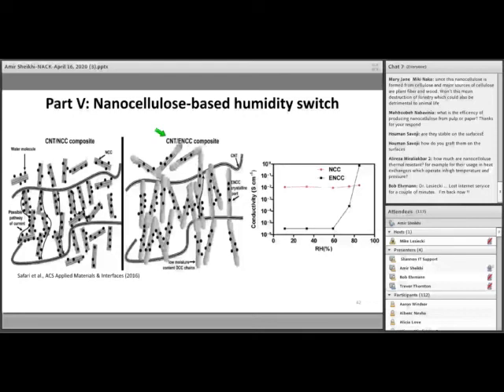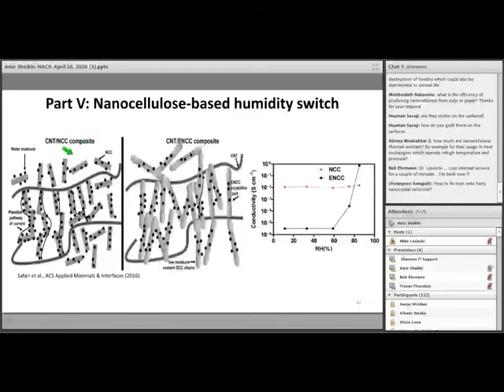Another interesting application is to use nanocelluloses for humidity switches. We can mix conventional nanocelluloses with carbon nanotubes, which are conductive, or we can mix these hairy nanoparticles with CNT. The conductivity of nanocomposites made of conventional nanocelluloses and CNT, as you can see here, is almost constant versus relative humidity. But with these hairy nanoparticles, the conductivity is noticeably low at low relative humidities, and suddenly, after 60% relative humidity, the conductivity starts increasing.